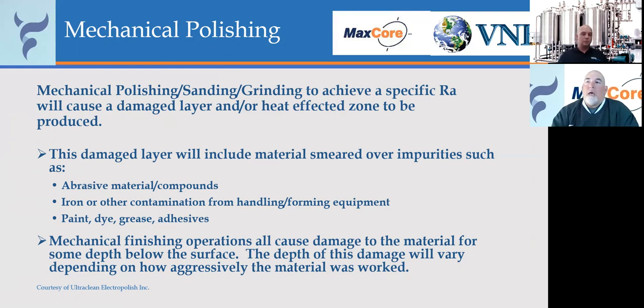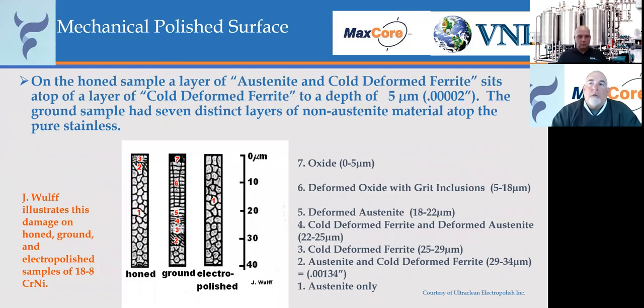There was a study done by a gentleman by the name of J. Wulff that looked at honed surfaces, ground surfaces, which are mechanically polished, and an electropolished surface to look at the different levels of deformation. What he found on a mechanically polished, ground surface was 7 different layers on the surface of that steel, anywhere from oxides to deformed ferrite all the way down to austenite. If you look at the electropolished surface, he found that all of that damaged layer was removed and the only thing left on the surface of the steel was austenite.